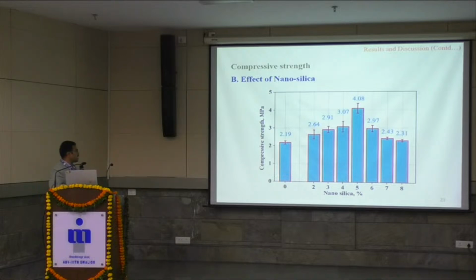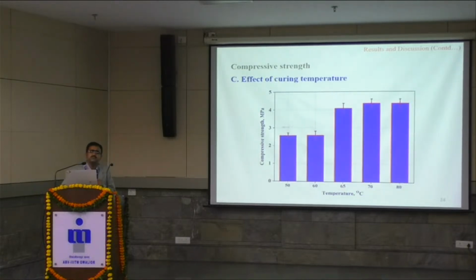When nanosilica was added after the addition of calcined white clay, up to 5% nanosilica, the compressive strength increases and then decreases, due to the agglomeration as well as the precipitation due to the excess, unreactive silica.